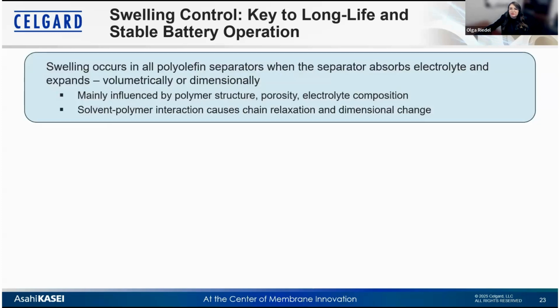A lesser known and lesser discussed contributor to long cycle life is actually how we control swelling in polymer membranes. Swelling is a natural occurrence in all types of polyolefin separators when the film is absorbing the electrolyte and expanding volumetrically in terms of thickness, but also dimensionally in terms of width and length expansion. This behavior is mainly influenced by the polymer structure and the porosity of the film. Solvent-polymer interaction causes chain relaxations and therefore dimensional change.